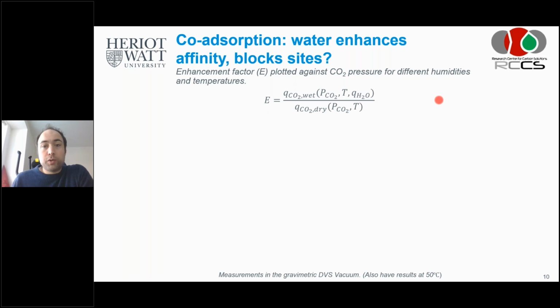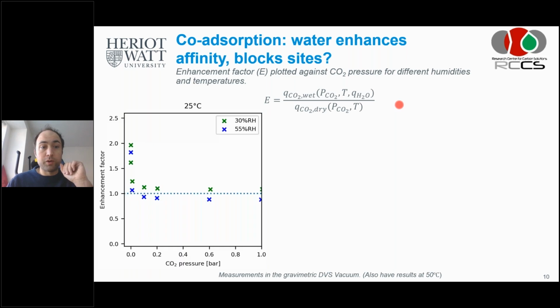And what I'm going to show you is the result of the co-adsorption experiments. Basically what I'm going to show you is an enhancement factor, one that shows the CO2 uptake in wet conditions versus the CO2 uptake in dry conditions. So how much does the presence of humidity enhance the CO2 uptake on your adsorbent?